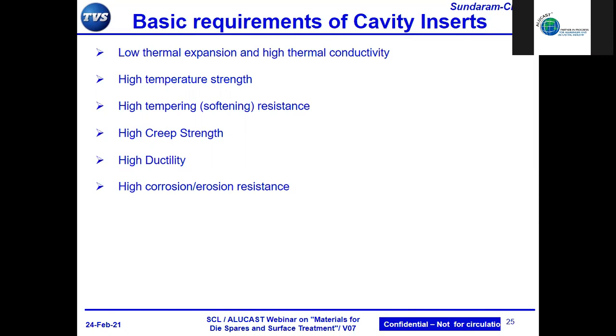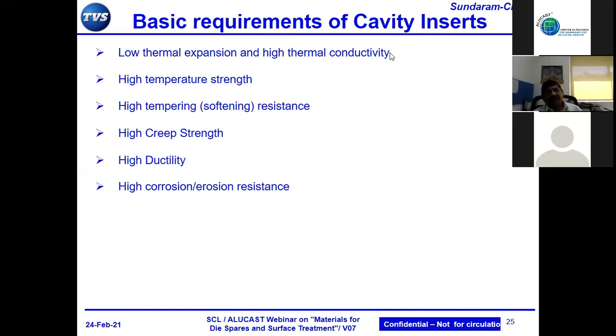So it should have a high ductility. If you do not have high ductility in these materials, you can have a catastrophic failure of these inserts or the dies. A ductile material gives you early warnings before failure. A combination of high strength and high ductility gives a high toughness steel. So that is how it is described, and you have a tough material on board. As I said earlier, corrosion resistance and erosion resistance are again basic virtues of a material that could qualify as a good tool steel, die steel for die casting.